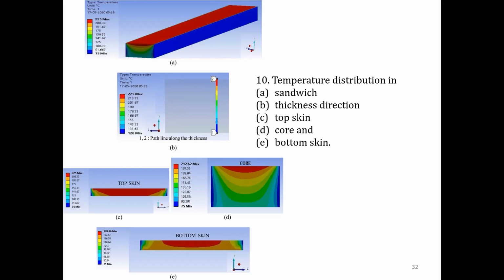Now, the temperature distribution along the thickness of the sample, you can see in figure B here. The temperature distribution of the printed samples, we all know, depends on the heat transfer coefficient of the surrounding air, nozzle, and bed, and definitely so the temperature gradient is made. By considering all these parameters as the boundary conditions, a steady state thermal analysis, as I was mentioning earlier, temperature variation is observed along the thickness and also in the radial direction.